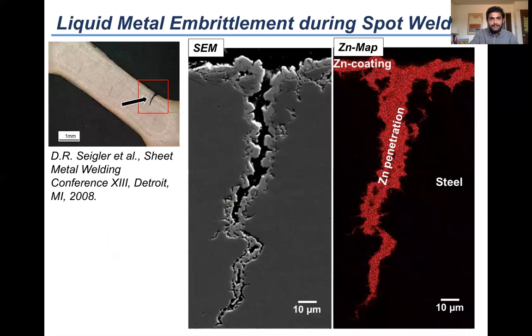And this problem is typically encountered during resistance spot welding. The picture to the left is a spot weld LME crack. When we analyze these cracks, this is the SEM image of the crack. This is the corresponding zinc EDS map, which tells us that the zinc from the coating has penetrated into the steel. So that's an LME crack.